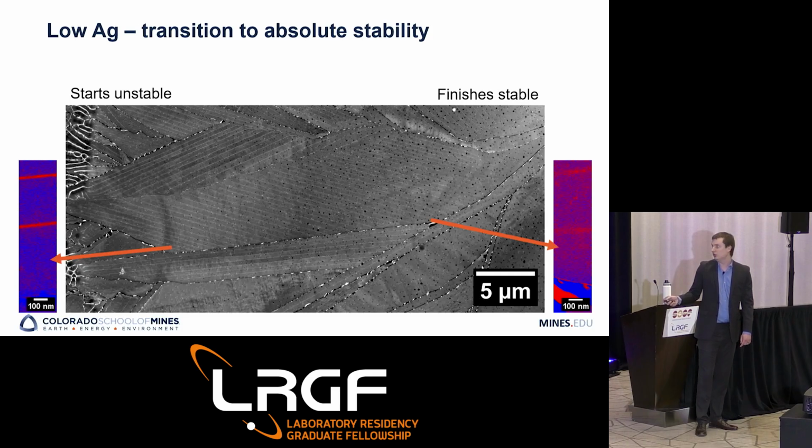And as you go further along into the solidification front, the velocity increases. And as that velocity increases, you eventually cross the threshold into absolute stability, which is what we call the velocity so high that you just stop partitioning and get a planar front. But it doesn't occur instantaneously. As we're approaching absolute stability, the partitioning coefficient decreases, and you can see a drop-off in how strongly partitioning the solid-liquid interface is before we go all the way to a non-partitioning planar front.